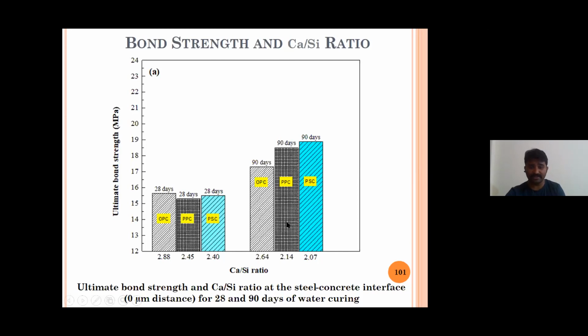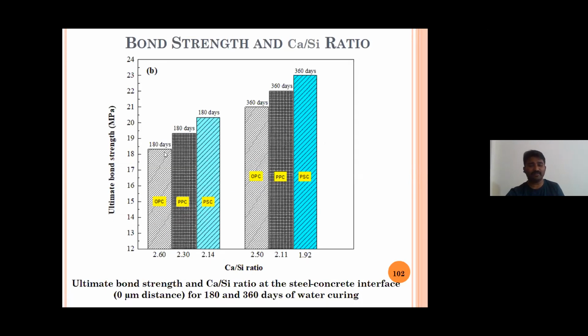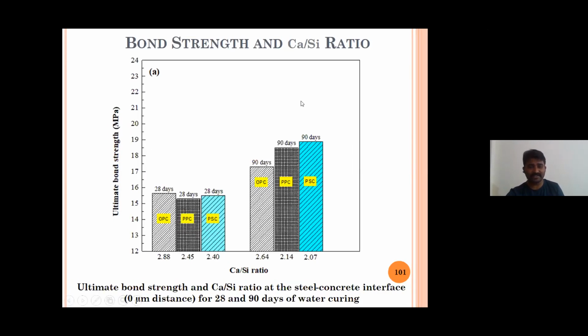As I move to 90 days, remember for the same OPC it was 2.88, it reduced to 2.6. For PPC it was 2.45, it reduced to 2.14. For PSC it was 2.4 and it reduced to 2.07. Because of this reduction, there is an increase in ultimate bond strength. Right? So from this we conclude that even for 180 days and 360 days, same thing, we have kept the y-axis in the same direction, 24 MPa.